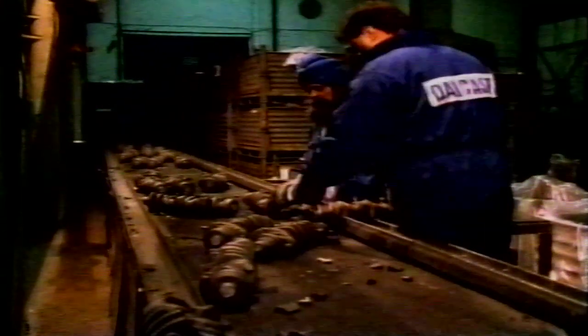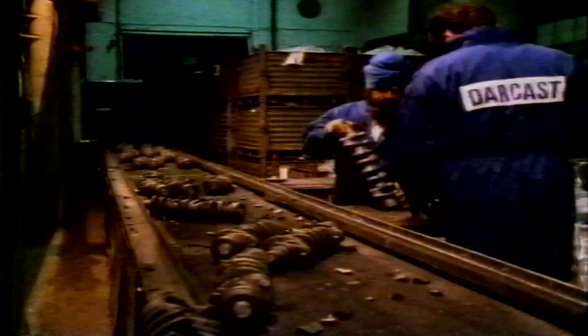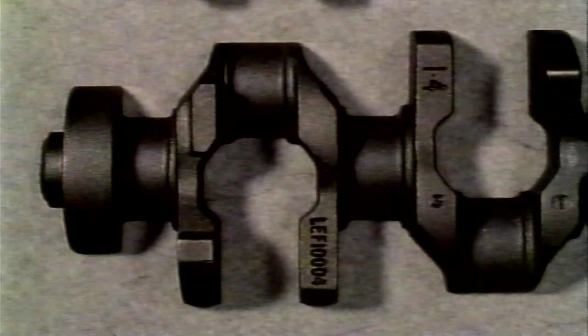This enables high production rates, up to 1,000 an hour to be produced. Although this foundry makes mainly crankshafts, over 2 million a year, the plant is relatively flexible, and other components could be made simply by changing the shell moulds. Indeed, crankshafts for a number of different engines and manufacturers are cast fully interchangeably in this foundry, with only the mould pattern changing. Of course, cast SG iron has a distinctly different microstructure to that of forged low alloy steel.